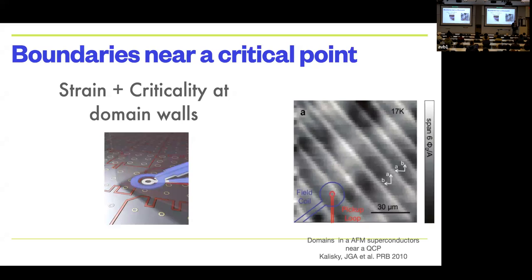So this was a bit of a surprise, and it's always haunted me. And it's haunted me for this reason. At these domain wall boundaries, that's where the structure changes from one direction to the other. So there's a lot of strain here, right? And we've already been using strain to try and probe the internal broken symmetries of these systems. In other words, the strain was coupling directly to the broken symmetry of the material itself. And now what I'm seeing is that the places where the strain is the largest, at these domain wall boundaries, that somehow is where the superconductivity is the greatest.